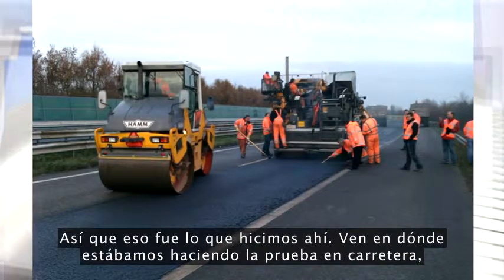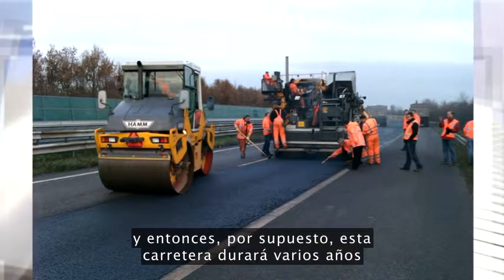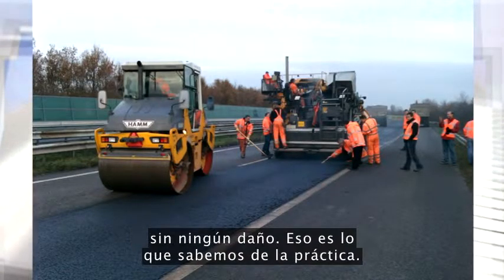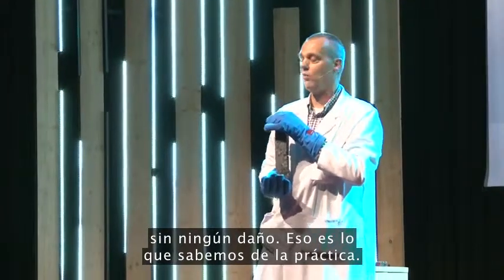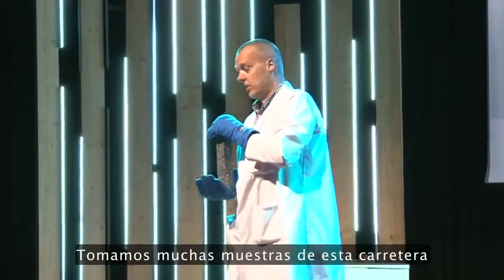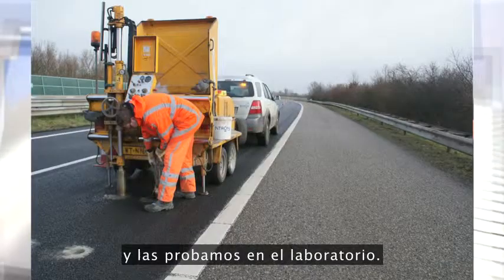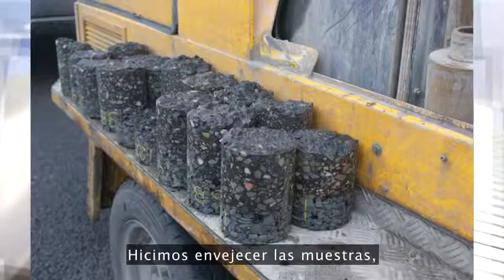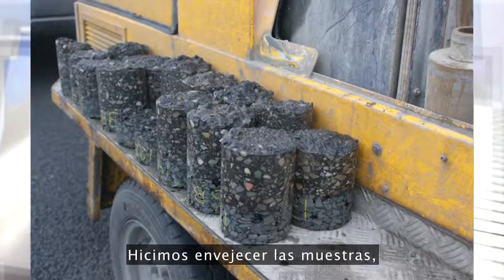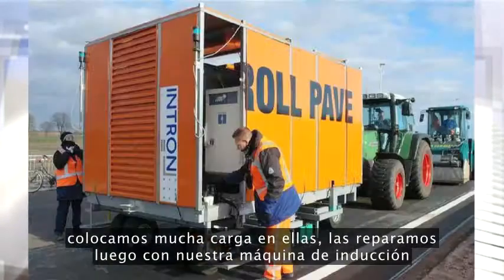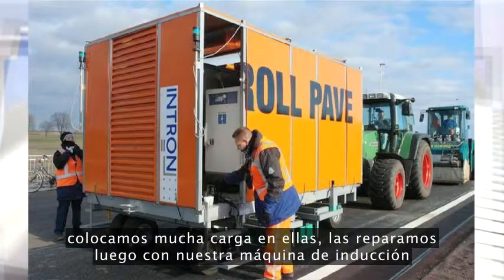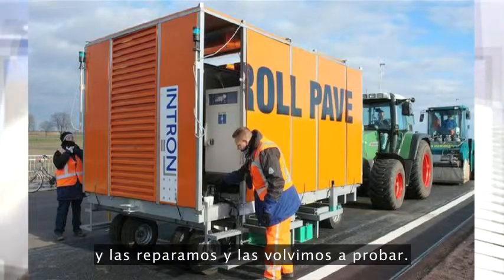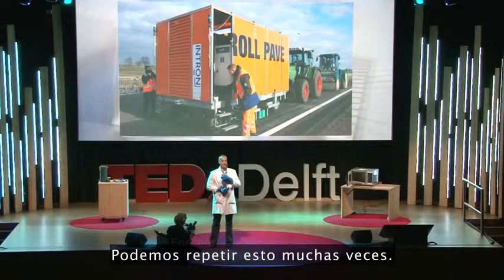You see where we're making the test road, and then, of course, this road will last several years without any damage. That's what we know from practice. So we took a lot of samples from this road and we tested them in the lab. So we did aging on the samples, did a lot of loading on it, healed them with our induction machine, and tested them again. Several times we can repeat that.